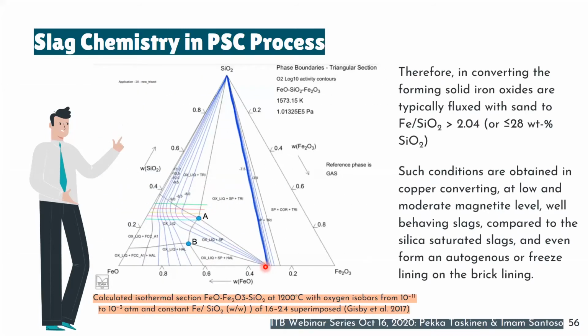Therefore, in a converting process, the slag is controlled to have an iron to silica ratio of around 2.04. Again, because iron in the slag can form as magnetite or wustite, we just use iron divided by silica, which has to be bigger than 2.04 in order to get the optimum conditions. And these conditions will also allow us to have very good slag.